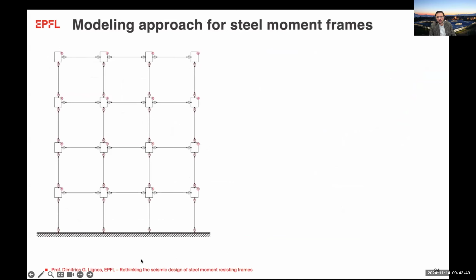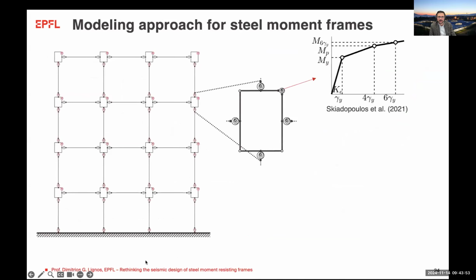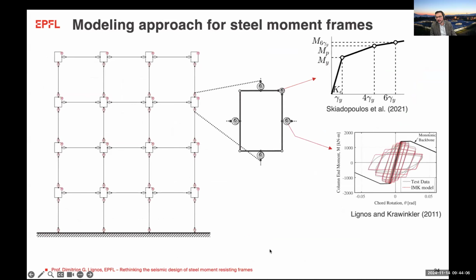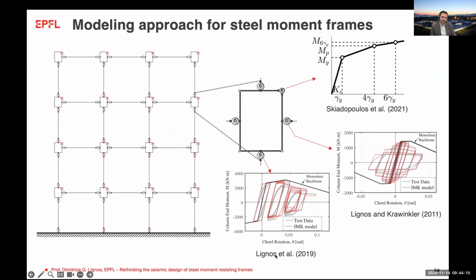And the modeling approach here featured obviously the panel zone. The model we used in the panel zone is a trilinear model that we predicted the parameters based on what I showed earlier in the first part of the presentation. Then we captured the potential of strength degradation in the beams as well as columns based on prior work that we've done in my group.